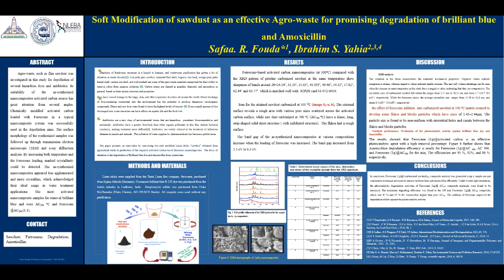Morphological analysis shows that SC2, as a representative sample, has agglomerates whose cavities were attributable to carbonized sawdust at 300 degrees. Diffuse reflectance and optical band gap analysis of the synthesized nanocomposite shows that the band gap varied from 5.5 to 6.3 electron volts.